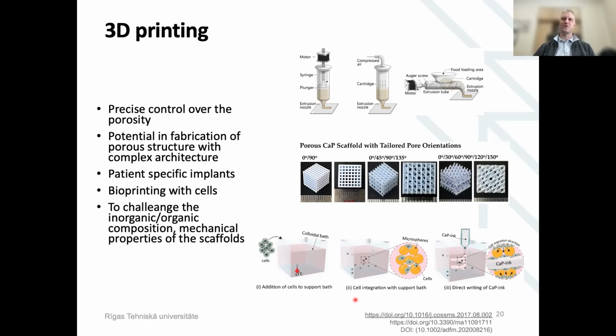And then I observed also one quite recent development, where in specific hydrogel baths they added the cells and then 3D printed in the volume the calcium phosphates, and they observed that the cells come on the surface of those calcium phosphates and form some kind of more bone-like structure. So this is something I think is part of the future technology. But we just should find a way to add really high mechanical properties to these printed structures.